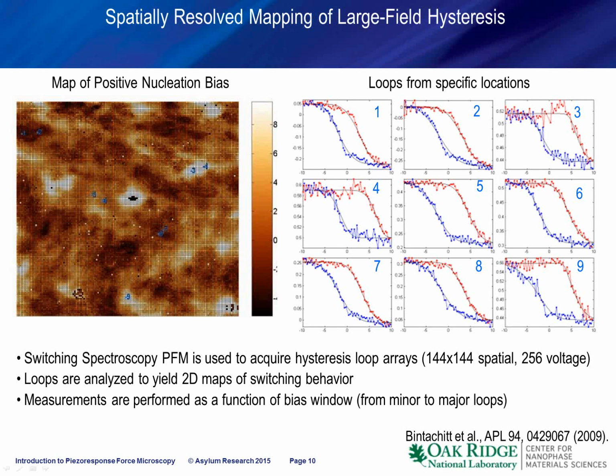What's remarkable is that in many capacitors we and other groups have studied, we observe the effect of clustering. So for whatever reason, the capacitors switch as if they're formed by effective grains much larger than the local crystallographic grains in the underlying film. So this presumably happens because of the strain interactions in the system, but this is one of those directions that still needs very extensive studies.